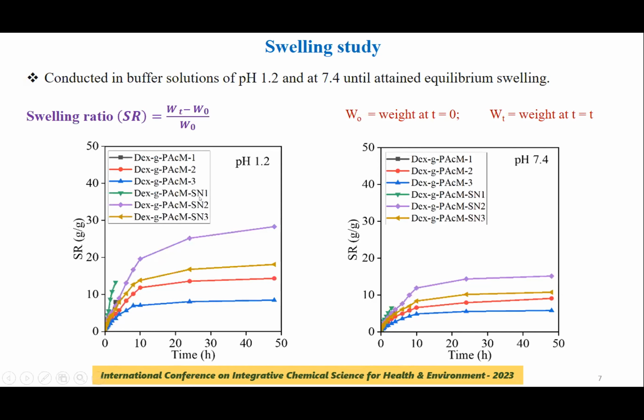And the fourth observation: formulation 1, 1 ml, for both hydrogel and nanocomposite, was unable to reach equilibrium because of the low concentration of ACM. It became very soft and difficult to handle, so we could not continue recording the weight. Based on the systems which attained equilibrium, system 2 for both hydrogel and nanocomposite swelled significantly more than system 3, and these systems were considered the best for further studies.